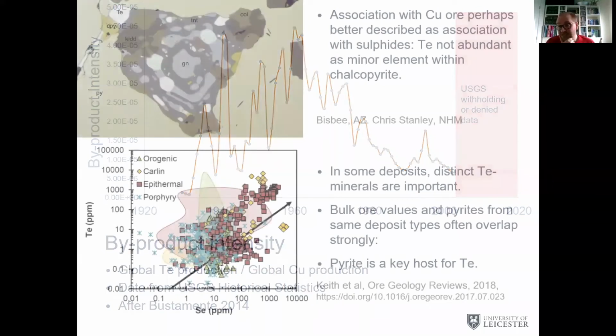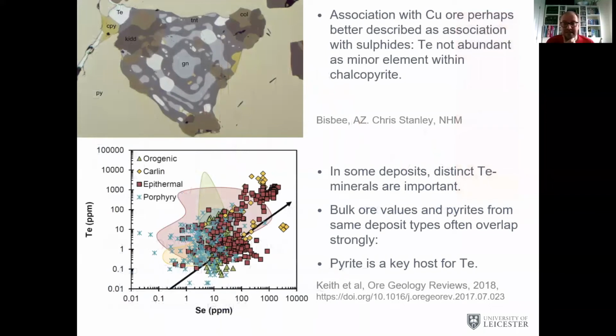So as part of our project, we did look at some copper ore, but it turned out not really to be very exciting for the TEAS project. Katie McFall, who's in the list of participants, will probably disagree with me here because she looked at some fabulously tellurium-enriched porphyry deposits. But some of the ones that we looked at from the Leicester team were pretty boring. In fact, the association with copper ore is a little bit weak. It's probably better that we describe tellurium as being associated with sulfide ores in general. In many of the sites that we looked at, we didn't find a particularly high concentration of tellurium in the copper-rich minerals, certainly not in chalcopyrite, which is the dominant copper mineral for most of the deposits that we looked at. Instead, we were seeing tellurium minerals in association with that ore, but not with the chalcopyrite.